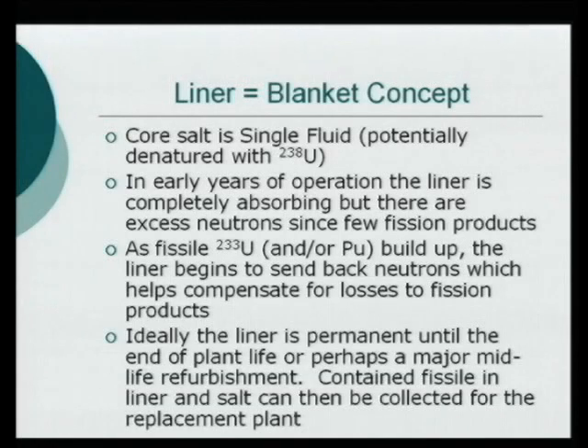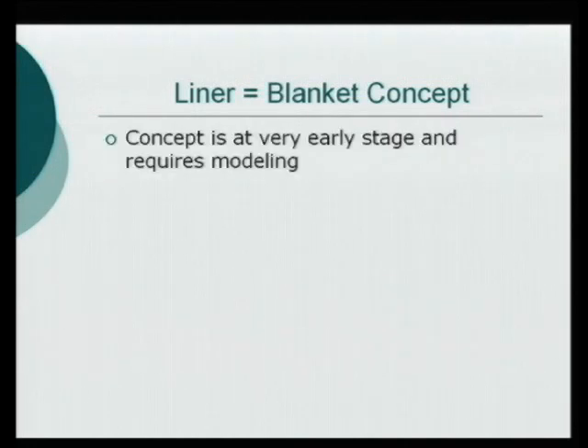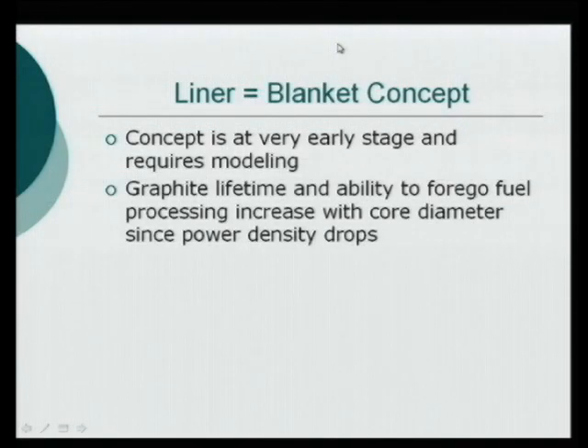So ideally, we could make this liner that's permanent. We don't have to replace that, or at least last, say, 20, 30 years and have a midlife refurbishment here. And also, hopefully, without any fuel processing whatsoever. Now, this is a very early stage, requires a lot of modeling, it's quite speculative. The graphite lifetime and the ability to get rid of fuel processing definitely goes up with the core diameter. If you make this absolutely enormous, it will definitely work.